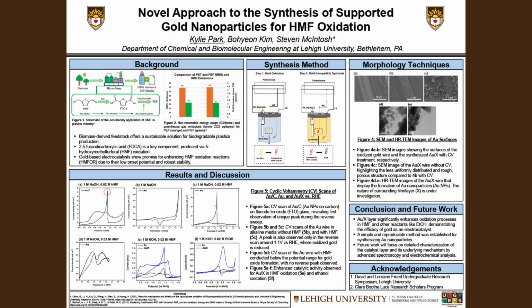Figure 5b is gold wire in 2 molar sodium hydroxide solution. The absence of significant peaks in the reverse sweep indicates there is no specific oxidation process occurring, and if there is, it's not as evident without the presence of HMF. In Figure 5c, we see a CV scan of gold wire in sodium hydroxide solution with HMF. The peak around 1.1 volts in the reverse sweep suggests the occurrence of likely the same electrochemical process found in Figure 5a, the reduction of the oxidized gold formed during the forward sweep.